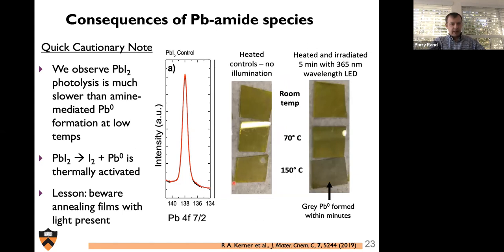And I should just, as an aside, note that this lead iodide control is really quite stable, and that photolysis or even thermolysis of lead iodide to I2 and lead zero takes quite considerable heat or light to activate. However, if we irradiate it simultaneously with heating it, we can start to see lead zero being formed rather rapidly. So in general, one should be very cautious of exposing lead iodide to simultaneous light and heat, because this can lead to rather rapid photolysis of lead iodide.